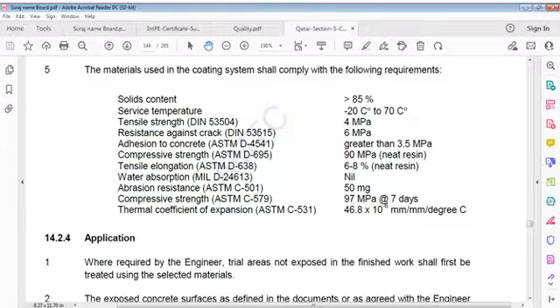Abrasion resistance 50 milligram. Compressive strength ASTM C579, 97 MPa at 7 days. 97 MPa.